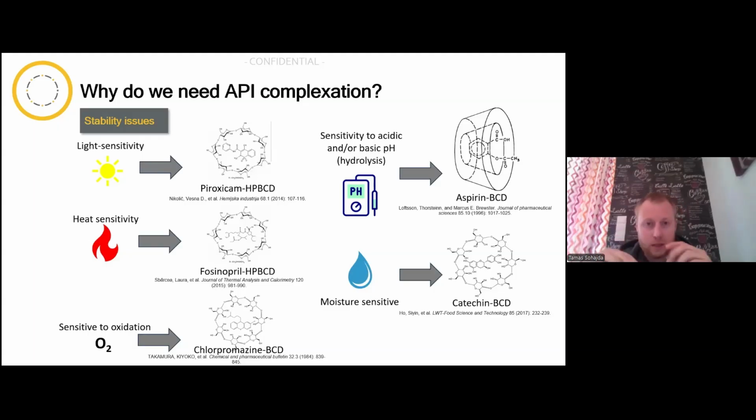So, if you make a solid, a tablet, or if you create a lyophilized powder in the vial, even if you create a solution, an eye drop, when it's in its liquid form in the container, it stays complexed. But typically upon administration, the equilibrium that we were talking about earlier shifts towards the dissociation. It always shifts. It's just a matter of how quickly and to what extent it shifts towards the dissociation. If it dissociates in the body, there will be a lot of competition, a lot of other agents and molecules around, a lot of much larger media.